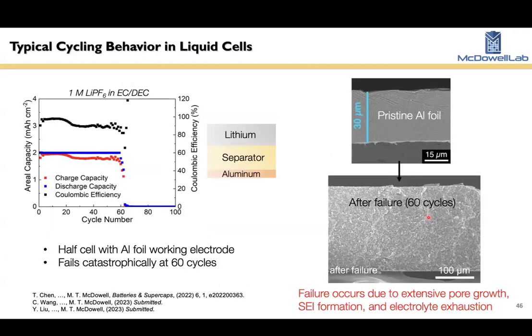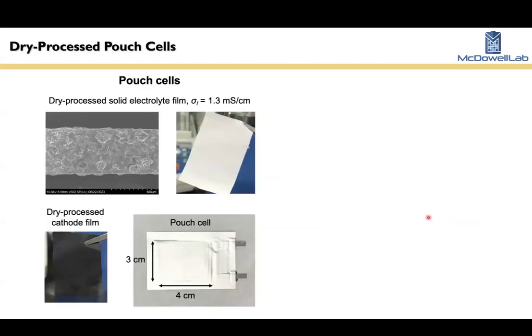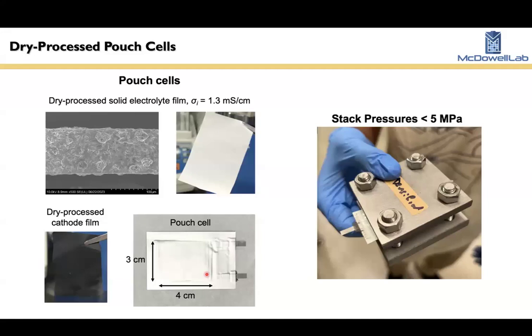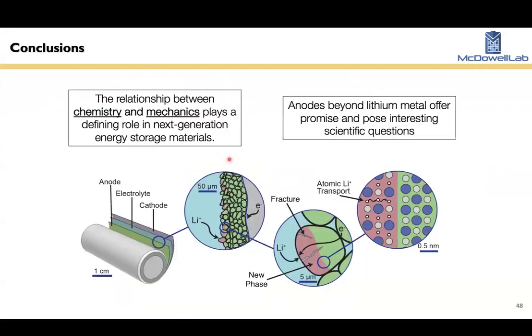And I'll just skip through this. This is testing in liquid cells. It's quite bad in liquid cells because of SEI formation. So what we're doing now in this project is building larger pouch cells. Everything I showed you was small scale, anvil type cells. We're doing dry processing of the separators and the cathodes, making larger pouch cells and testing them at low stack pressures. We've developed some interfacial coatings that allow us to go to less than 5 megapascal stack pressure and achieve good cycling as well. So this project is moving towards demonstrations at a much larger scale that are necessary for thinking about commercial applications.